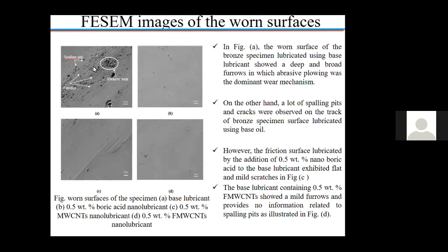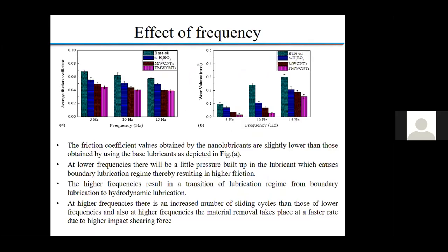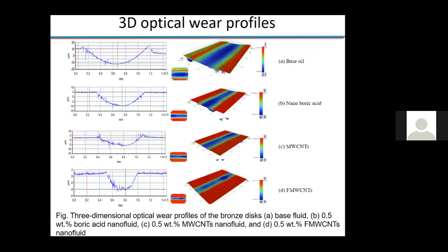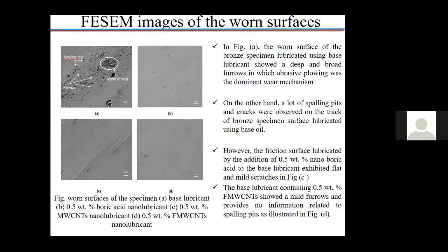Okay, so these are some images of worn surfaces. You can see the wear severity for all 4 cases. For functionalized multi-wall carbon nanotubes, there is minimum wear. Wear is there, but it is at a very minimum level. So the optimum results were obtained for 0.5 weight %. Initially we started from 0.25%, then 0.5, 0.75, and 1%. Among these percentages, 0.5% provided the better results.